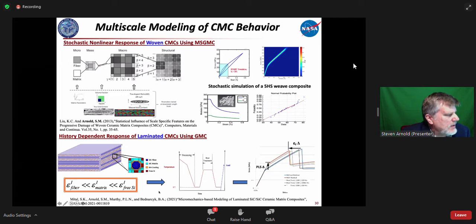Okay, and then with respect to laminates, we've done a significant amount of work on predicting the history-dependent response of laminated CMCs. Here we're showing the influence of processing histories and heat treatment on the subsequent tensile behavior of a CMC. And here we're taking into account 4 phases: the fiber, the matrix, the BN coating, and free silicon that resides within the silicon matrix.